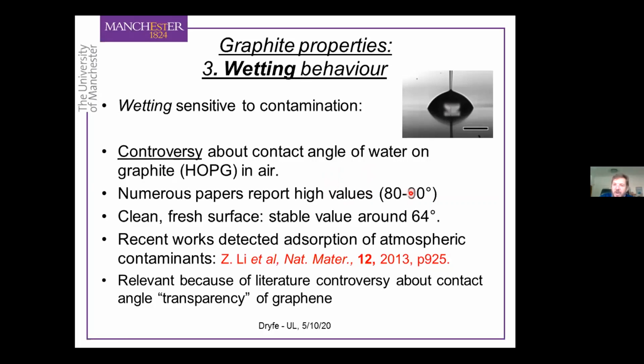And in fact, a lot of the numbers cluster around 80 or 90 degrees, but a few numbers, including our data more recently, which I would of course say is more reliable, but I'm biased, are more like the values we see of about 64 degrees. But there are a few other people who report similar values. And why this discrepancy? Why are there so many reputable papers giving this much higher value for what is quite a simple experiment? You put a droplet on a graphite surface and you measure its contact angle, which should be very simple.